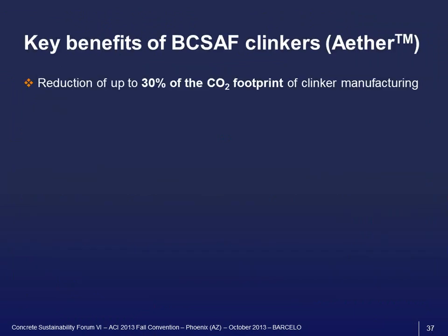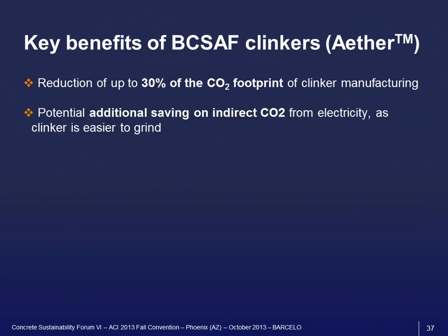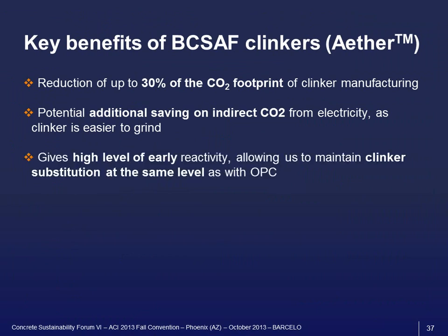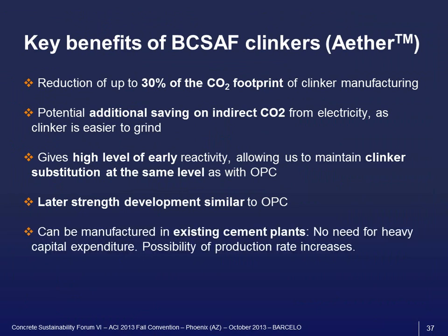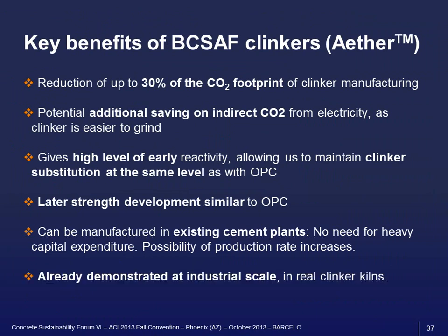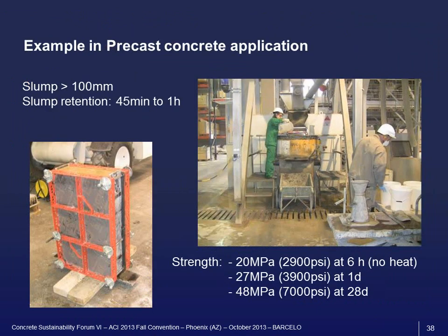So the key benefits of this, so first, as we've seen, 30% reduction of the CO2 footprint. We have an additional saving on CO2 from electricity because these clinkers are easier to grind. We have a high level of reactivity that allows to maintain a high level of SCM substitution. So we are not making trade-off on that aspect. We have a later strength development that is similar to OPC, and it can be manufactured in existing cement plants. We don't need heavy capital expenditures, and we can even potentially increase production rates because we are decreasing the burning temperature. And we have already demonstrated that at industrial scale in real kilns, both on older generation and on newer generation type of kilns.